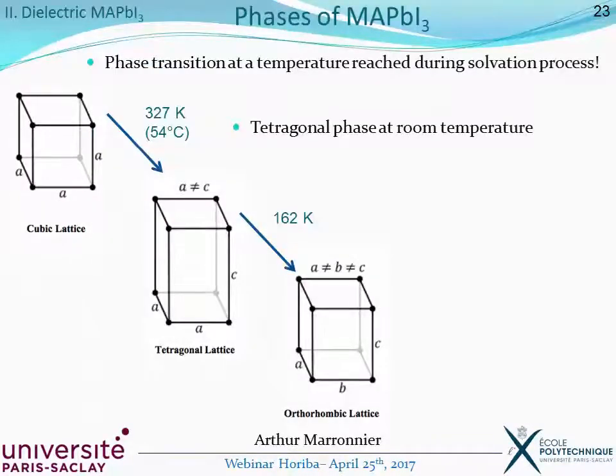Again, you have different phases, with the cubic phase at high temperature and the tetragonal phase being the stable phase at room temperature. What is important to notice here is that the transition from cubic to tetragonal happens at a very low temperature, around 50 degrees Celsius, which is actually a temperature reached during the solvation process, which can be problematic. But here on the calculations, I focused only on the cubic structure.